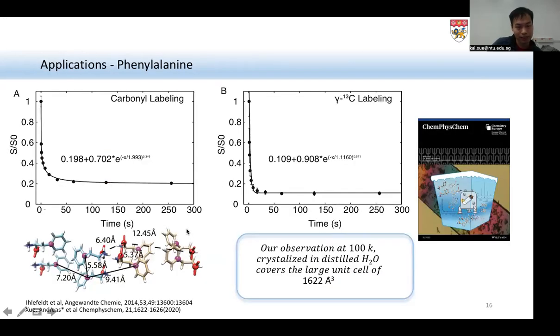Although this is the last slide, I think this can give us a very interesting number, because we actually did this paper to verify a crystal structure determined by crystallographers in 2014. Phenylalanine has been studied for quite a long time, but it is very interesting and unique. It forms many different crystals according to variations of crystallization conditions. In our system, when we selectively label carbonyl sites, we have a decaying curve that reaches approximately 20% of the signal and reaches a plateau. Only if we label on the gamma site, we reach this 10.9% plateau, which indicates the Z prime value of 8.